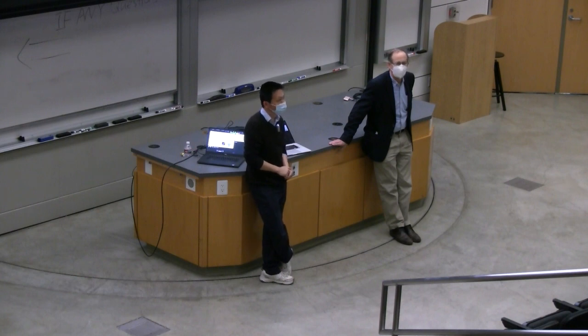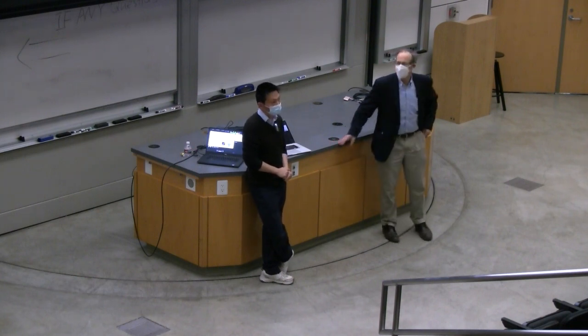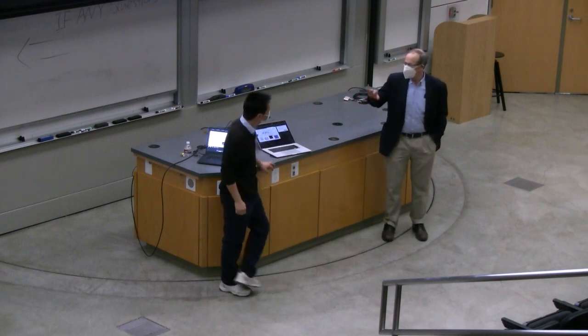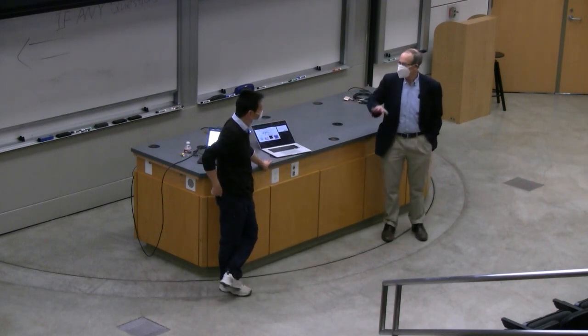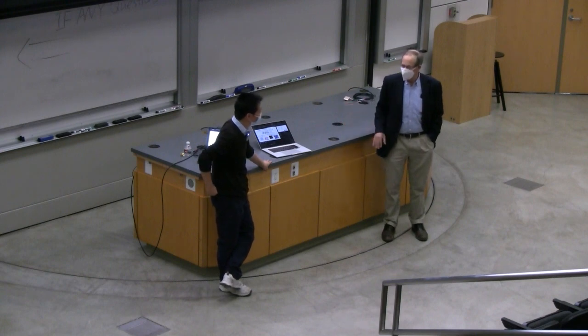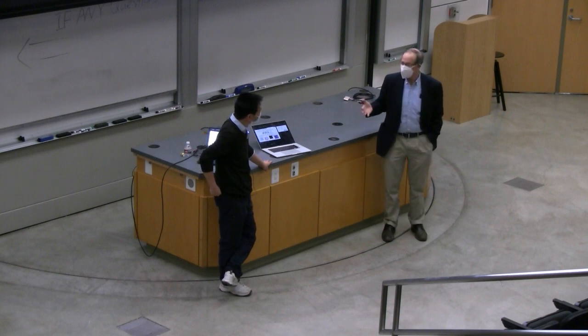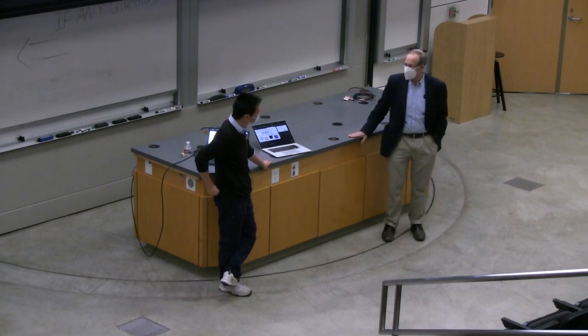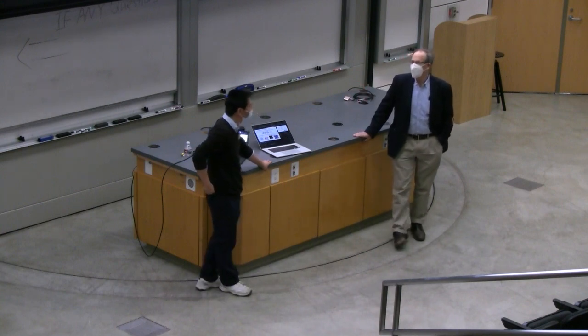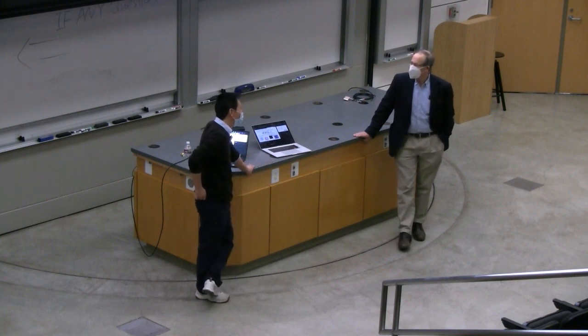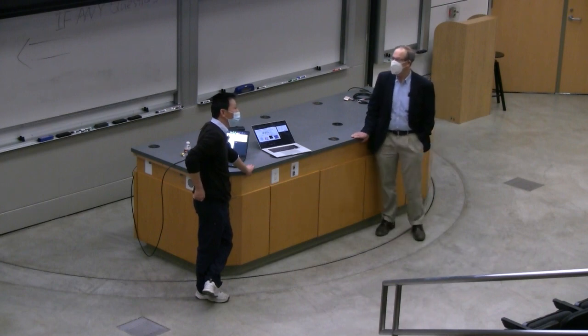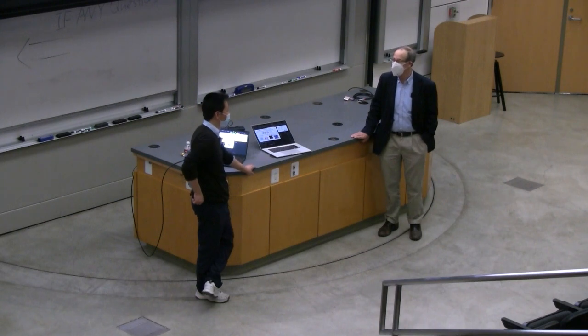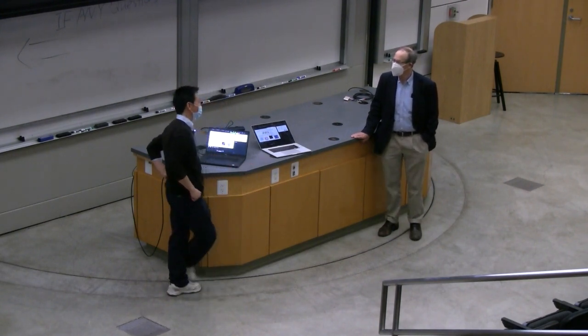Feng, may I ask you, you worked your way down to an extremely simple thing at one point, which was no Moire, just looking at the intrinsic formation of Wigner crystals. And if I look at the history, the new thing seems to be looking with an STM, this non-perturbative mode through graphene. But what does that tell you about the likelihood of Wigner crystals existing in typical bulk crystals? Because the argument is really not that different. It depends on the dielectric screening and the mass, but it doesn't seem fundamentally very different.